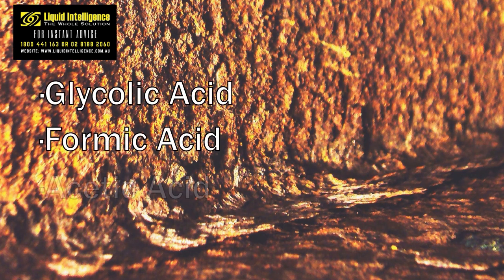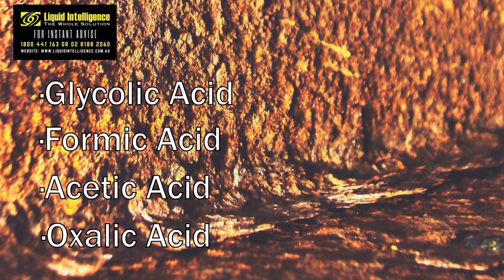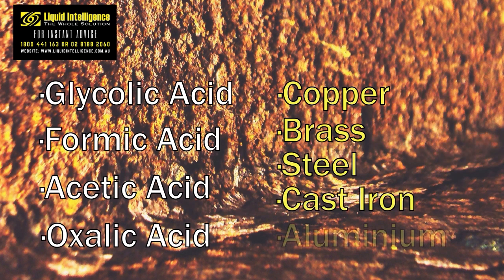Studies have since shown that ethylene glycol naturally degrades slowly in the presence of oxygen and high temperatures, conditions typically found in any cooling systems. During this degradation, several acidic byproducts are formed, including glycolic, formic, acetic, and oxalic acids. These acids can rapidly corrode metals found in cooling systems such as copper, brass, steel, cast iron, and aluminium.